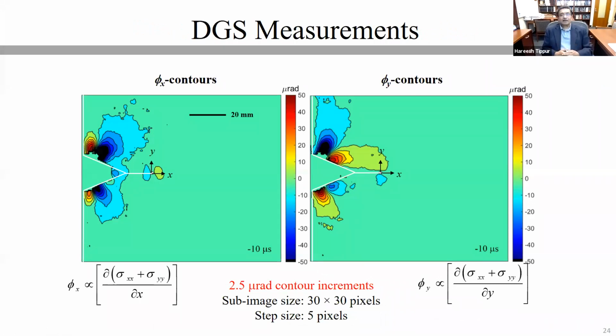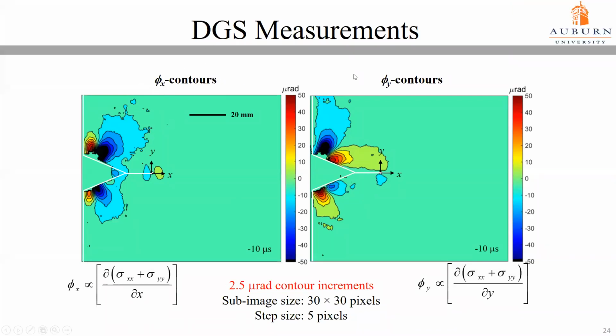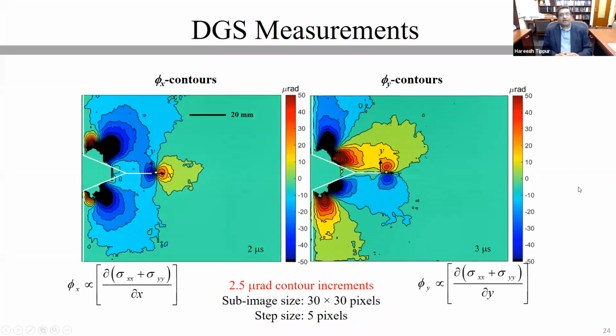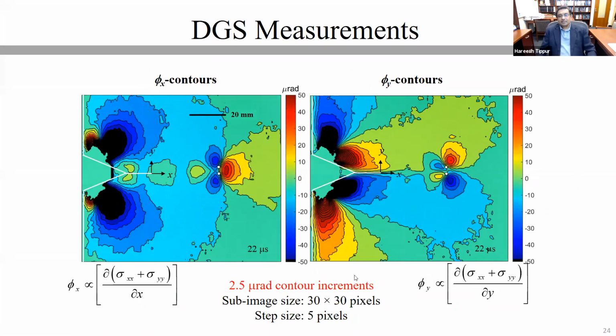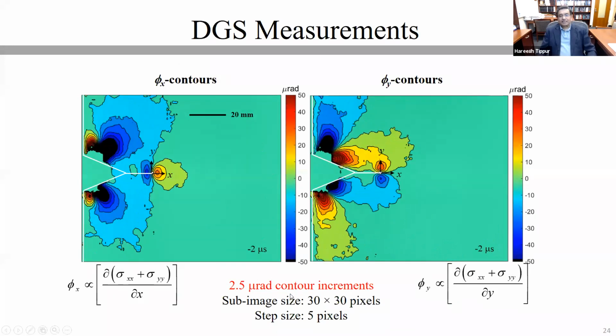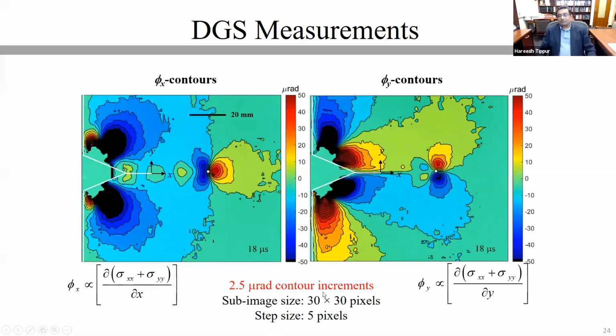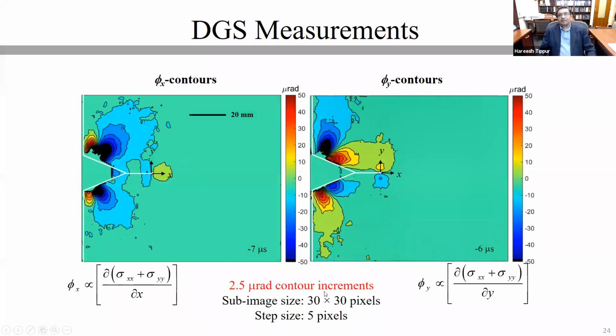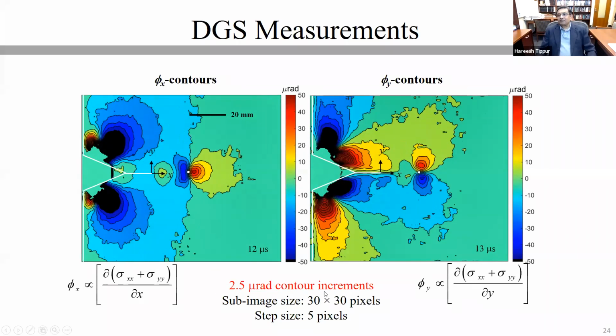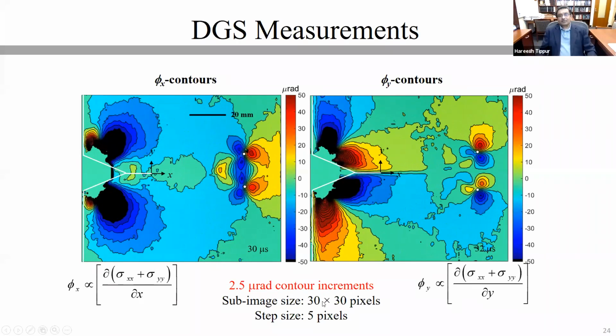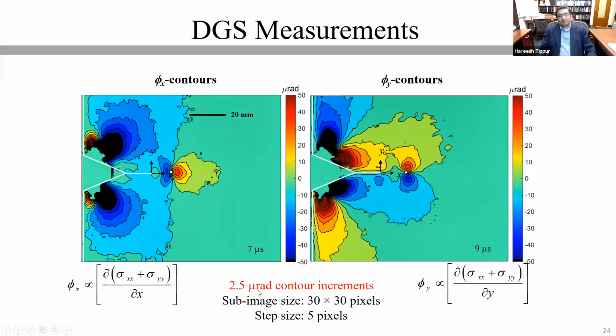When you do the post-processing, all you're doing is correlating the speckle image at each time step with the speckle image before the loading actually began. And you will be able to see contours of these angular deflections. These contours of angular deflections can also be animated. I'm plotting these as contours. These contours are in 2.5 microradian increments. To give you some idea of 1 microradian, it is the angle subtended by 1 millimeter at a distance of 1 kilometer. So that is as small as 1 microradian.